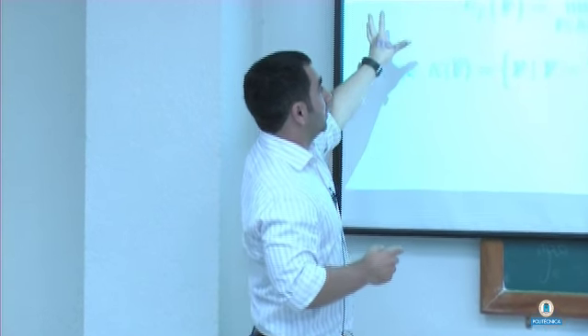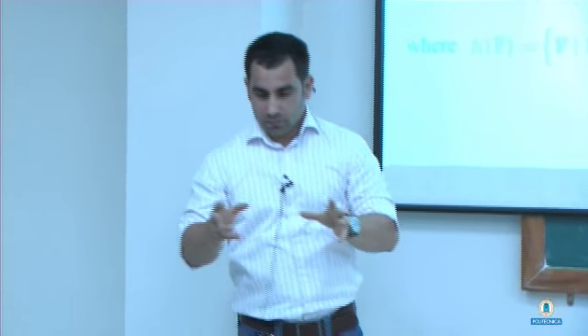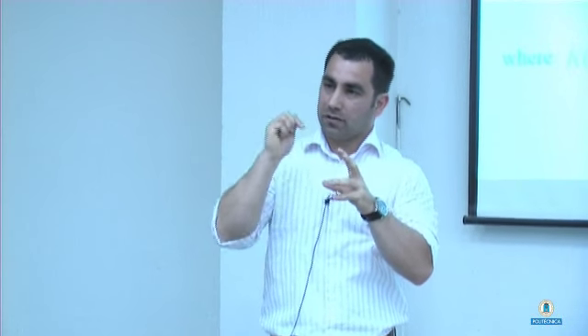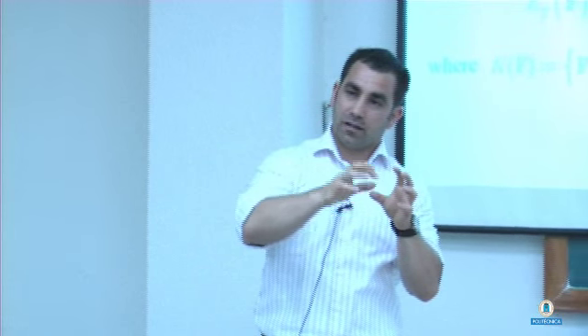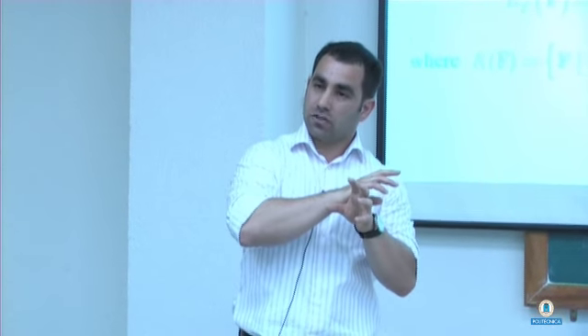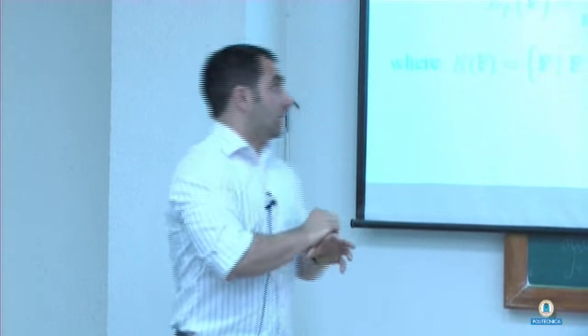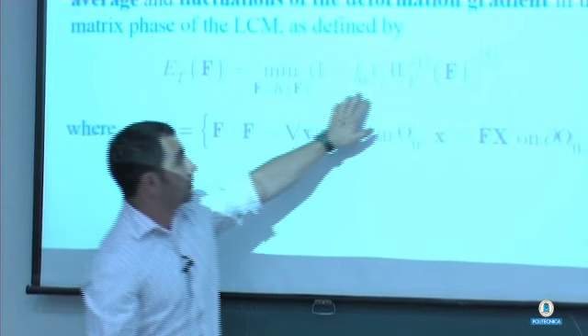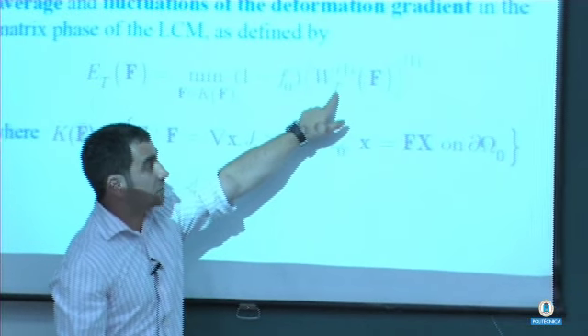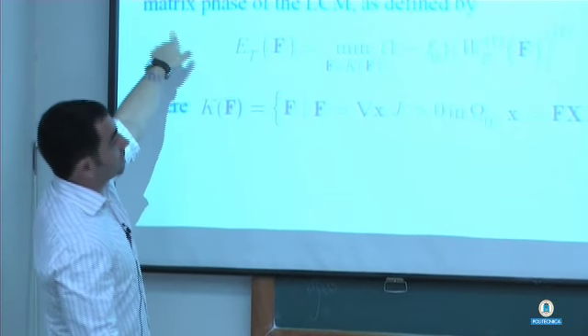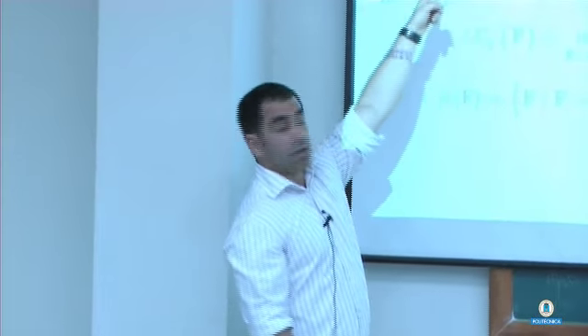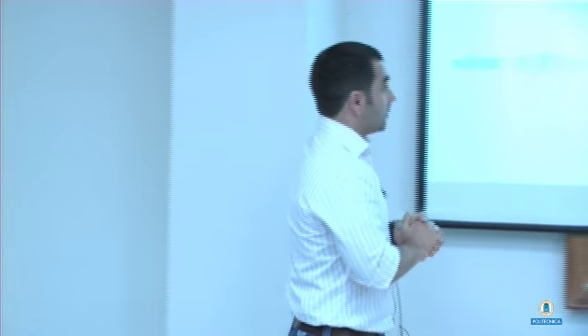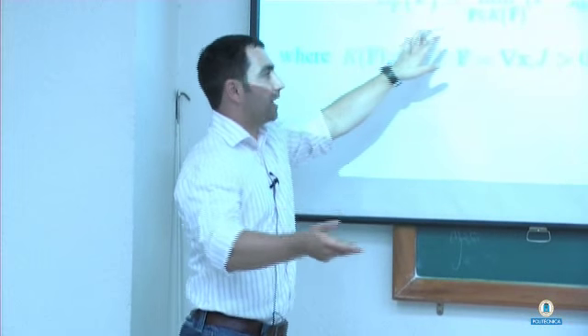So what you need to do is solve the same problem that you want to solve in reality, where the matrix is hyperelastic. You need to solve it now for the case where the matrix is this quadratic potential. All right? So now you have to solve a linear problem. Once you solve this linear problem, essentially this is what you want to do: solve the total elastic energy of a linear problem. This W is now the quadratic potential. Once you solve this, you can compute the fluctuations, the average. Really, you can compute anything you want, and you can put it in that formula, and that gives you the total elastic energy. Okay? All right. Now, so the problem kind of reduces to solving this homogenization problem in this linear problem.